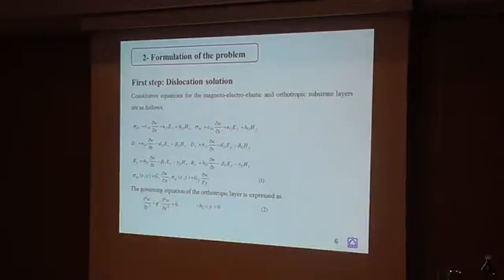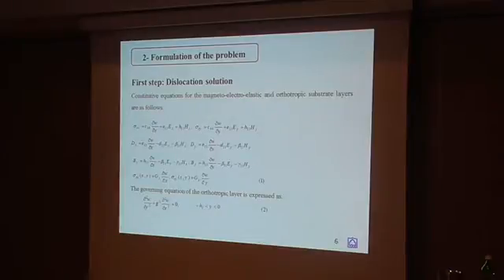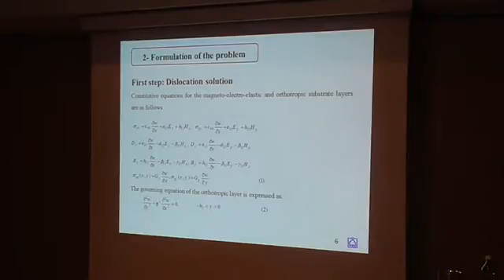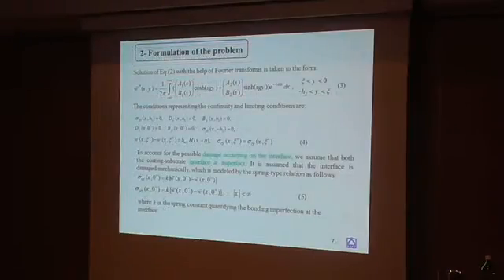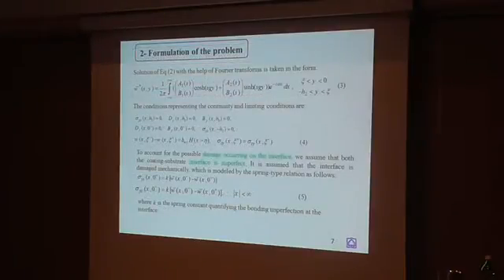At the first step, we use the distributed dislocation technique to solve the problem. The constitutive equations for a magneto-electro-elastic layer and an orthotropic substrate layer are presented in equation 1. The governing equation of the orthotropic layer is expressed in equation 2. The solution of equation 2, which contains a crack in an orthotropic layer, is obtained with the help of a Fourier transform, taken in the form of equation 3.